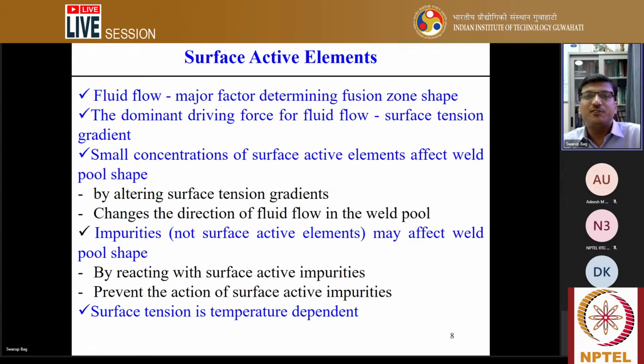For example, when there is an application of the surface active elements, it actually tries to change the material flow pattern within the small molten weld pool. That flow pattern actually decides the shape of the fusion zone. The dominant driving force for the fluid flow is mainly the surface tension force. So basically, surface active elements modify the nature of the surface tension gradient, and once the surface tension gradient changes, it influences the flow pattern. It can even change the direction of the surface tension gradient, positive to negative or negative to positive. That gradient actually decides the flow of the molten material from one point to another point.